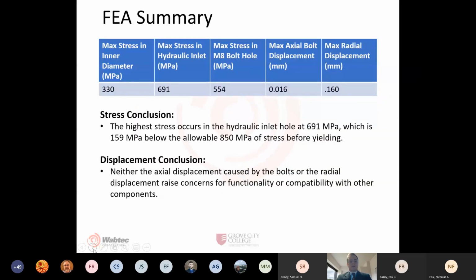So this is our finite element analysis summary of the collar. The highest stress occurs in the hydraulic inlet hole at around 691 megapascals, which is about 160 lower than the allowable 850 before the collar begins to yield. All other stresses in the critical areas fall well below the allowable stress. Also shown here is the axial bolt displacement and the radial displacement. These values are acceptable and small enough so that they don't raise concerns for functionality.